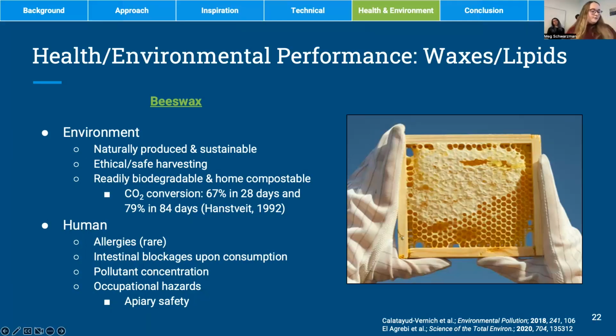A lot of large commercial bee farms, unfortunately, utilize techniques like wing clipping and artificial insemination to increase their output. But working with local harvesters, we should mitigate those concerns, but it is of utmost importance to make sure that we're not introducing an environmentally friendly alternative while doing damage to the environment subsequently. In terms of biodegradation, we looked at a study from 1992 that found carbon conversion rates of 67% in 28 days and 79% in 84 days. So those do meet both of those standards that I mentioned at the beginning of my section.